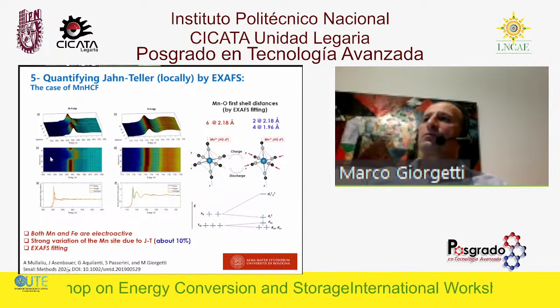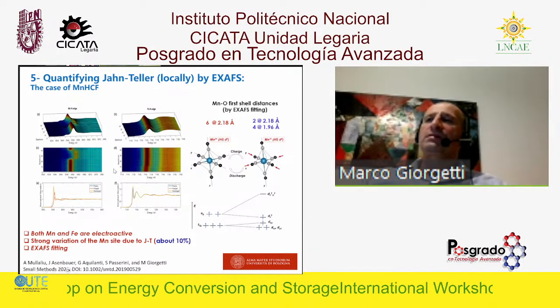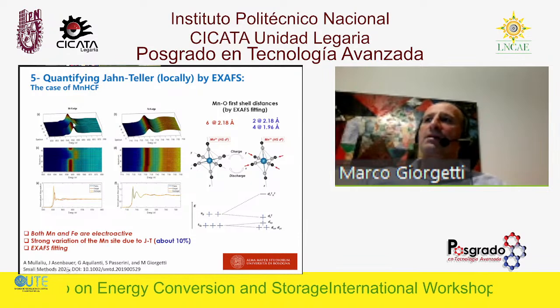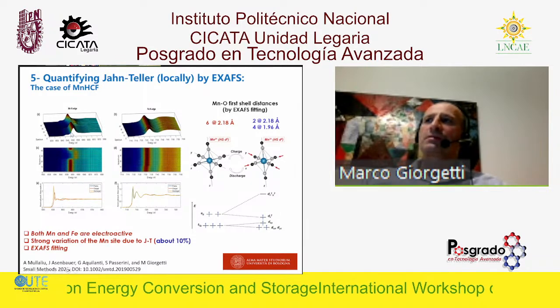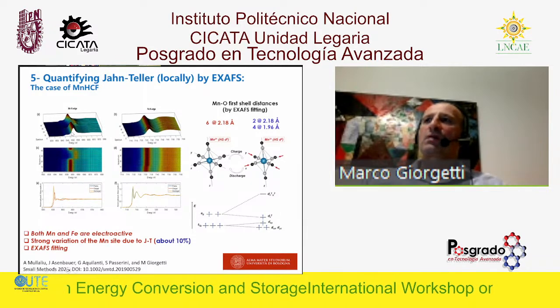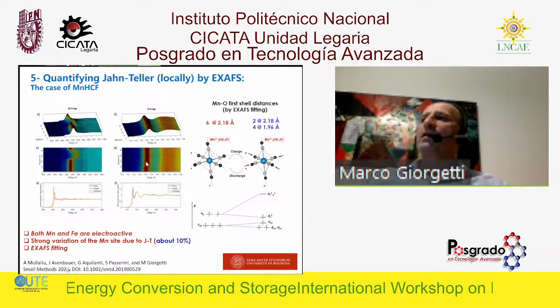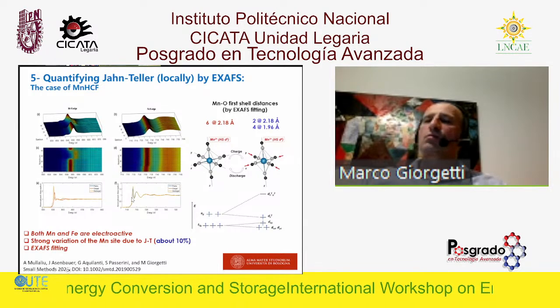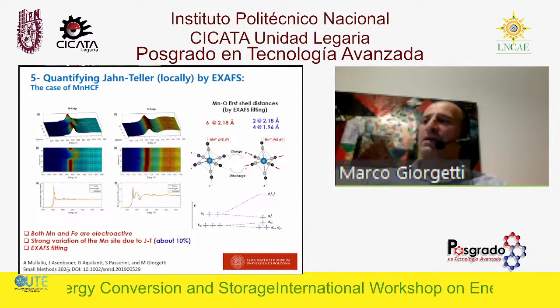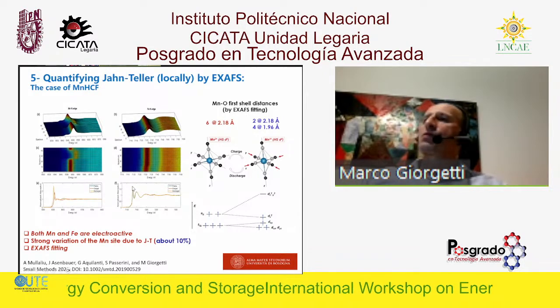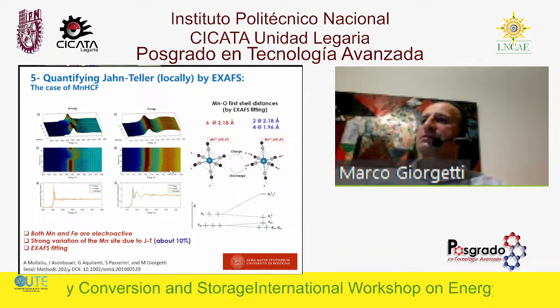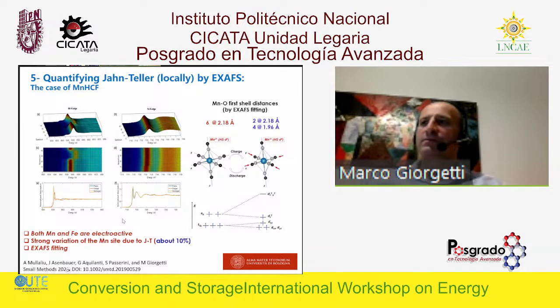First is to check the metal electroactivity of the manganese. And the manganese shows dramatic changes. It's really incredible, the changes that we have with the manganese. On the iron, basically, there is just a shift towards oxidation and reduction, and that's it. And so we concluded from these figures that both are electroactive.